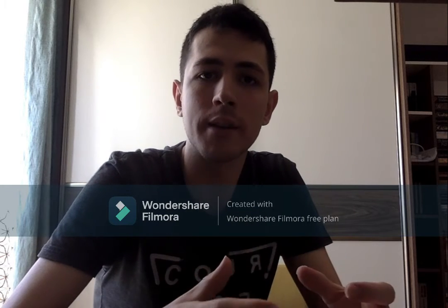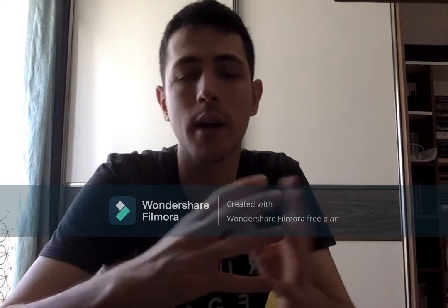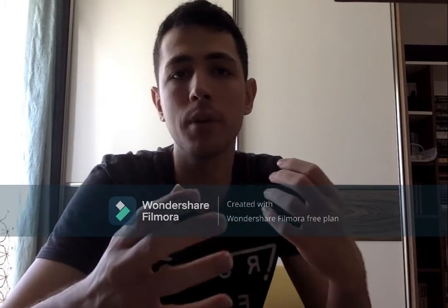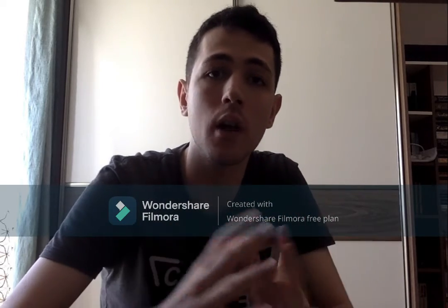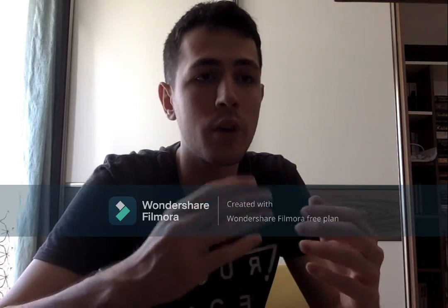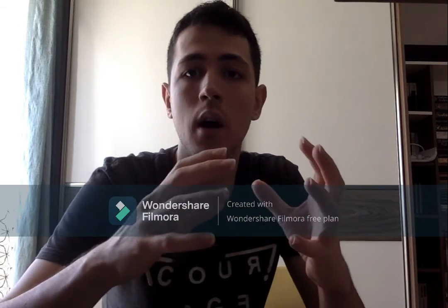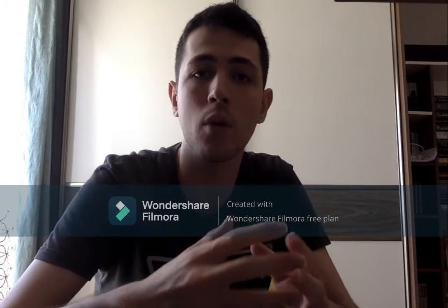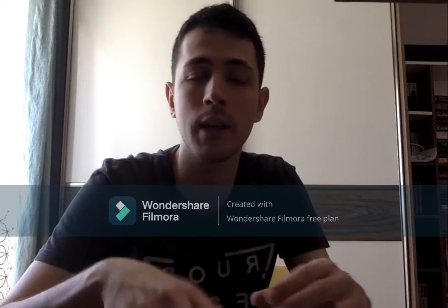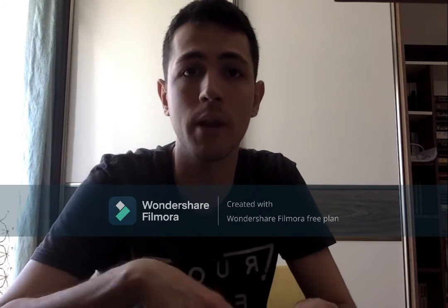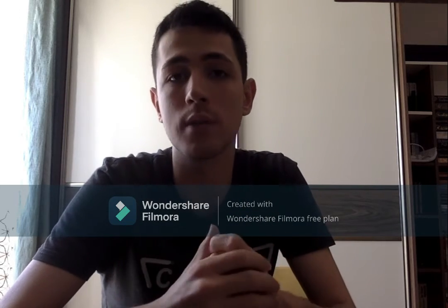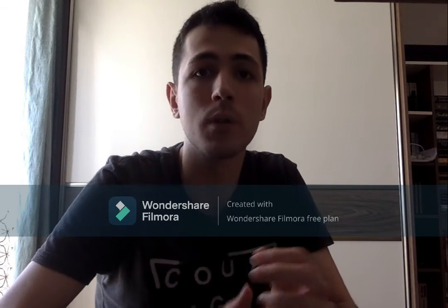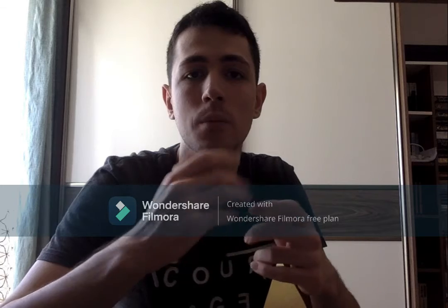As seen from the tests, a relatively small tensile load was adequate to separate two lids from each other in the half area case. In the full area case, on the other hand, the lids couldn't be separated from each other by application of a tensile load alone, but together with a torsional load. Therefore, it is plausible to deduce that with increasing welding area, the welding strength increases and it gets even more difficult to separate two lids from each other.